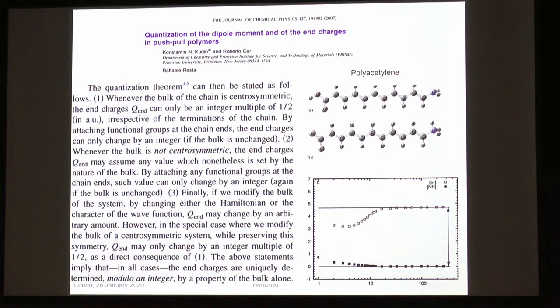And the other thing I want to say about this example is if you actually put a wire from one end to the other to conduct charge from one side to the other, then you would get zero again for the centrosymmetric case for sure. It's only when you have open circuit conditions that there's an issue, and in almost all condensed matter calculations for infinite systems, we have effectively shorted surfaces, because we find a single Fermi level for the whole system, which essentially shorts the system at the surfaces.